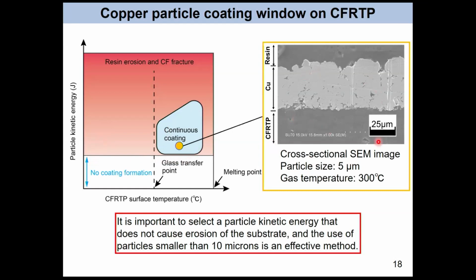This SEM cross-sectional image is the 5 micron particle size and 300 gas temperature case. We can see no carbon fiber fracture occurs, and mechanical interlocking may be the coating mechanism. So it's important to select a particle kinetic energy that does not cause erosion of the CFRP, and the use of small particles smaller than 10 microns is an effective method. But smaller particles sometimes easily cause clogging. So in our case, 5 microns is the lower limit. We also tried a 3 micrometer particle size, but clogging occurred and we could not realize stable powder feeding.